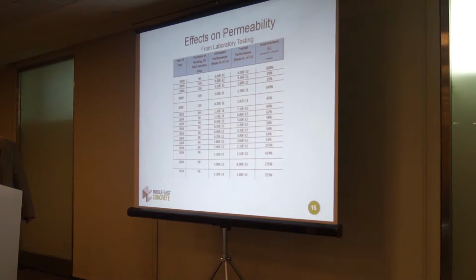So from laboratory testing, this is, again, University of Tennessee Chattanooga lab, as well as several others. The effects on permeability were mostly done by, in fact, all of these were a test method called AASHTO T259, which is the chloride ponding test. Depending on the mix, some of these were run for 90 days. Some of them were run for 120 days, and in one case, out to 365 days, to show the changes. And this is just chloride diffusion coefficient calculated using second order Fickian diffusion equations. So you can see that there's quite a bit of improvement. Some of them were tremendous improvements, and then some of them were less.